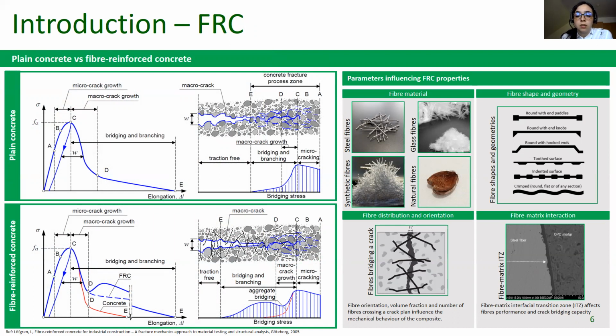An important role is also played by the fiber-matrix interaction and especially by the interfacial transition zone between the fiber and the matrix, because this is affecting the short-term and long-term mechanical performances of the composite.